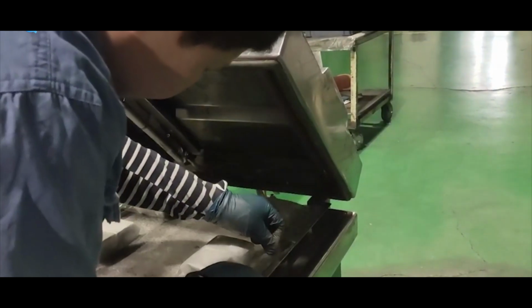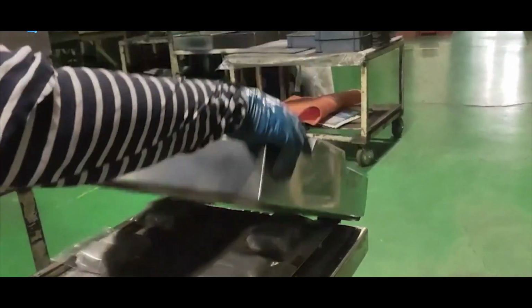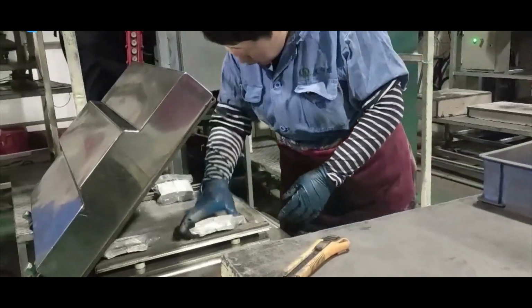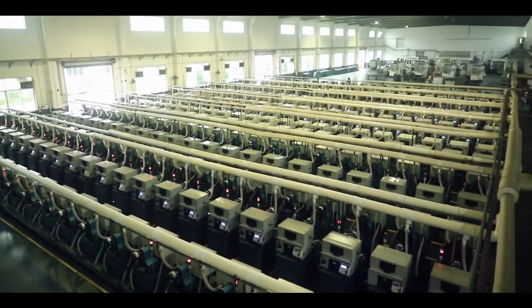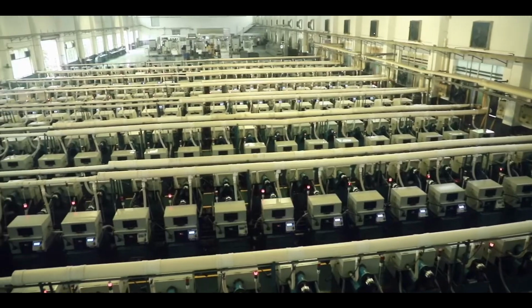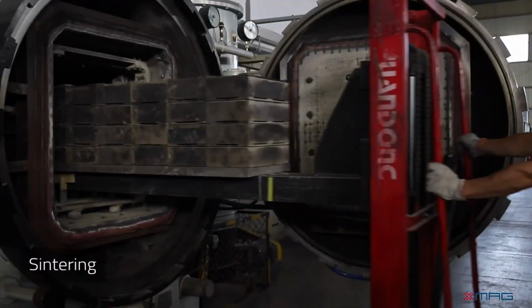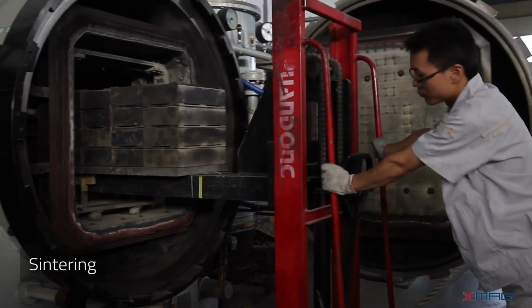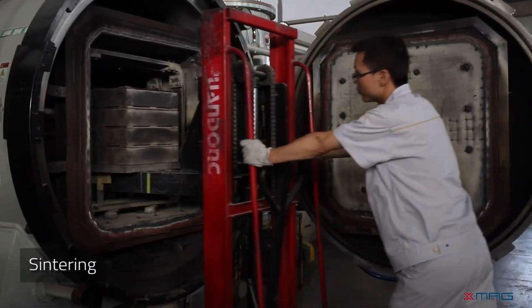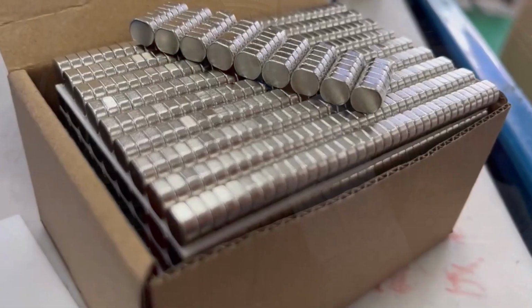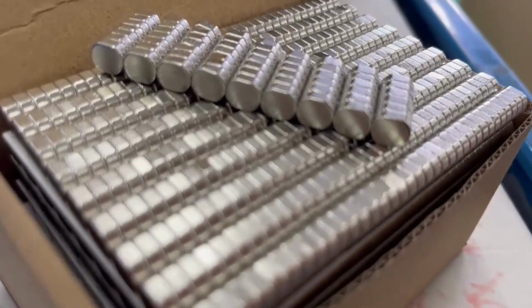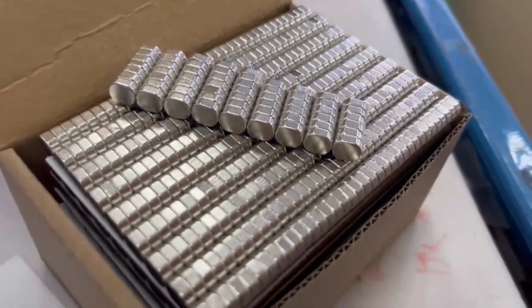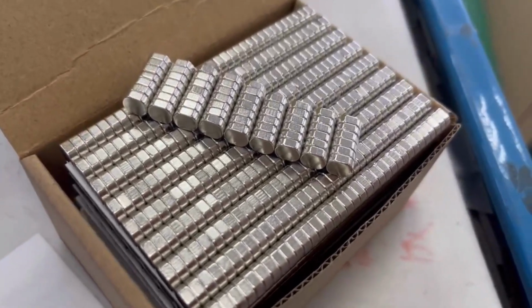The particular temperatures and presence of vacuum or inert gas is specific to the type and grade of magnet being produced. Both rare earth materials are heated to a sintering temperature and allowed to densify. SmCo has the additional requirement of a solutionizing treatment after sintering. After reaching room temperature, both materials are given a lower temperature tempering heat treatment.